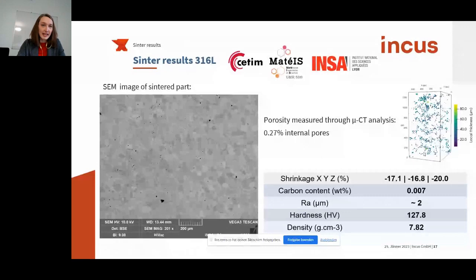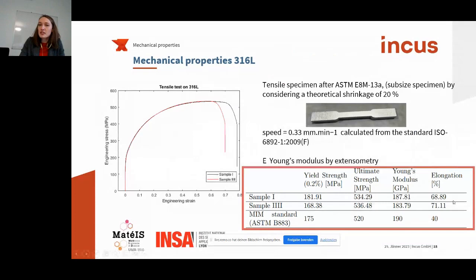In terms of mechanical properties, I would like to concentrate more on this little table down here. We have the MIM standards written in the bottom, and if we compare it with the samples that the INSA Institute measured, we are always within the same numbers as the standard in metal injection molding. The only thing where we exceed a little bit is elongation, but this is usually adjustable by the different cooling temperatures after the sintering. But in this case, it's more a positive sign than a negative one.